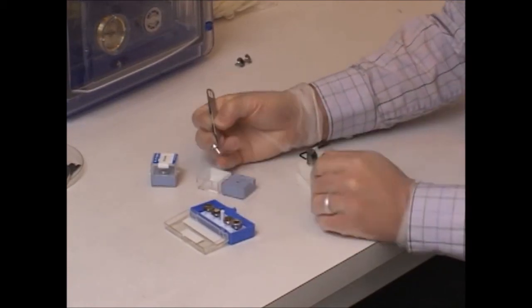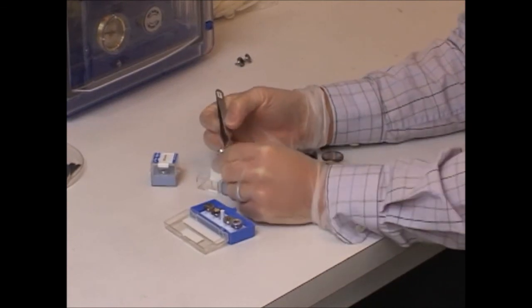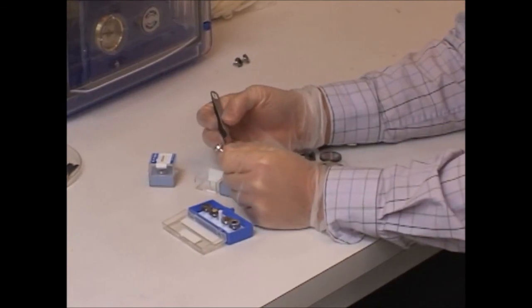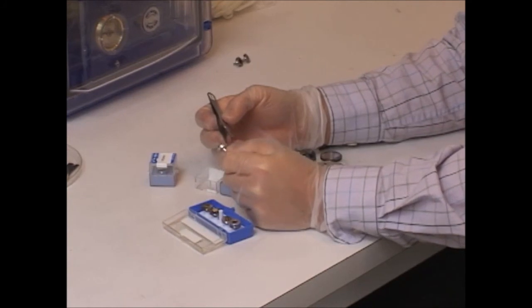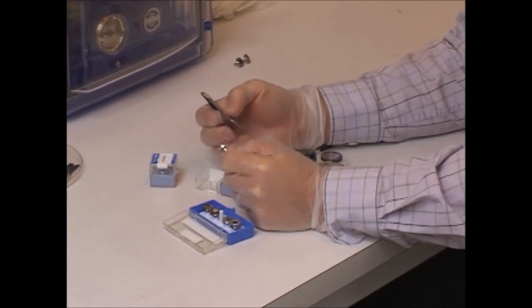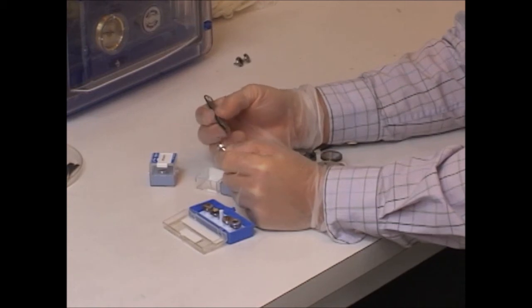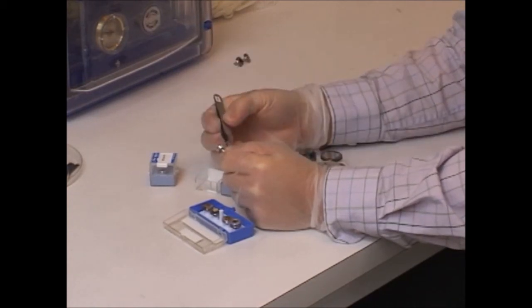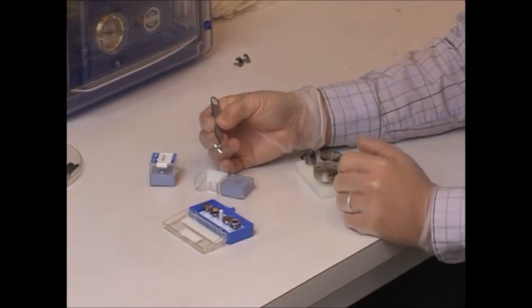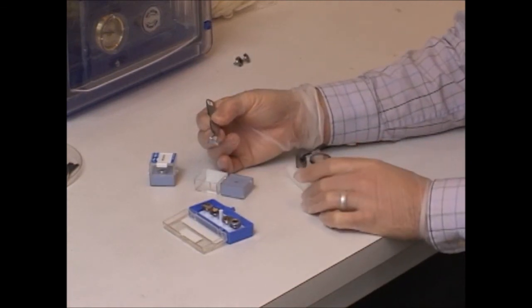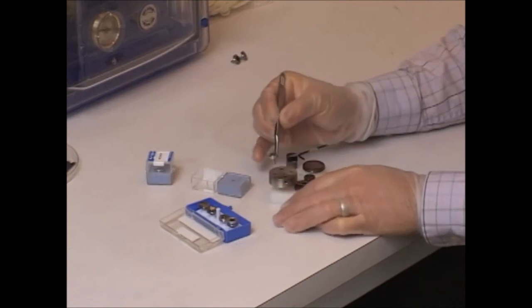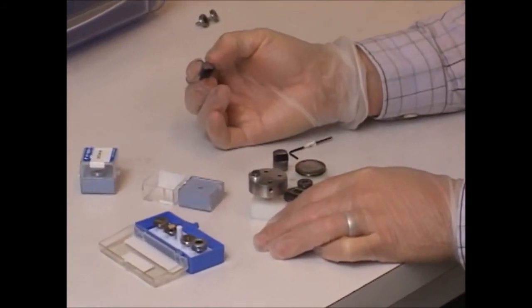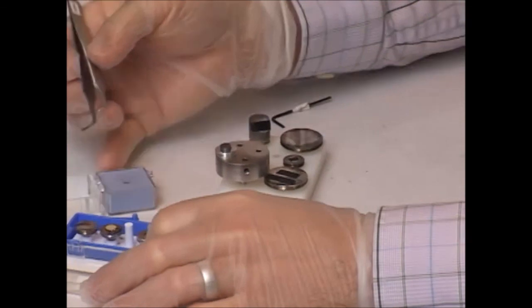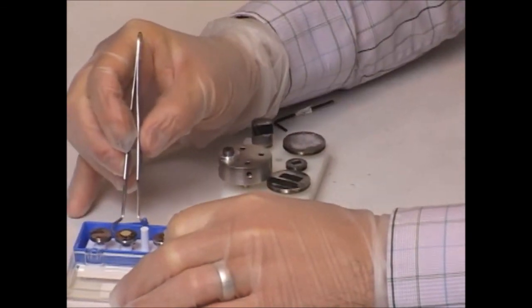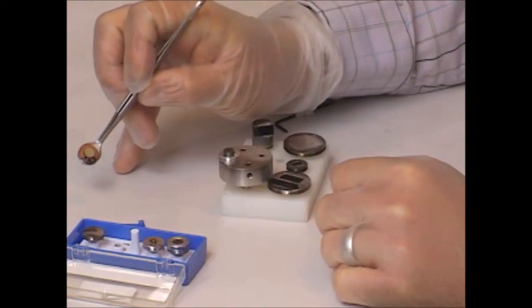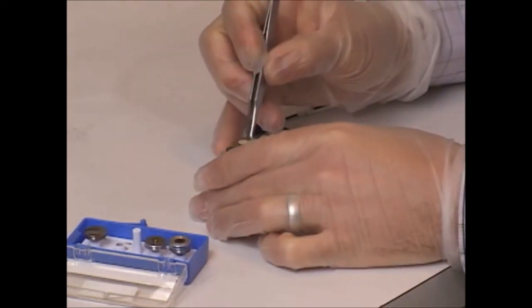And you can see that I'm handling it with a pair of tweezers. Each sample has a small groove in the side. If we were to actually touch the surface of the sample, we would cause a lot of damage to the thin film that's deposited there. So in order to avoid damaging the sample, handling with these tweezers in the groove on the sample holder is the best way to manipulate these. So I'm going to place the gold nanoparticles on the top position. And then I'm also going to put a sample of tin spheres to the right of it.